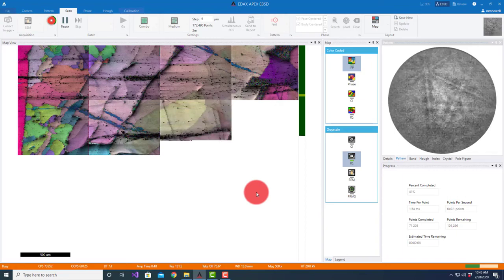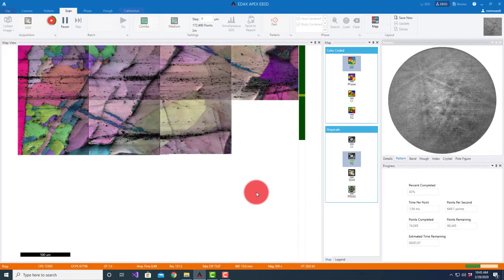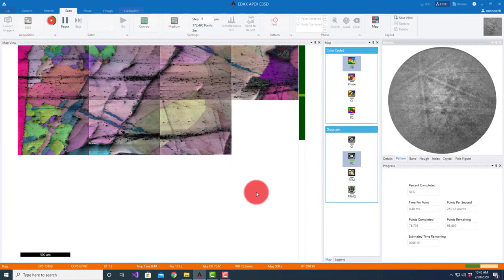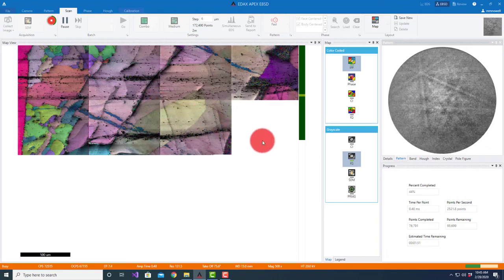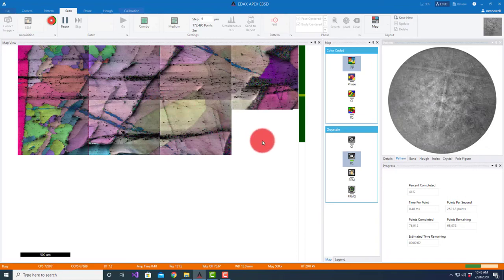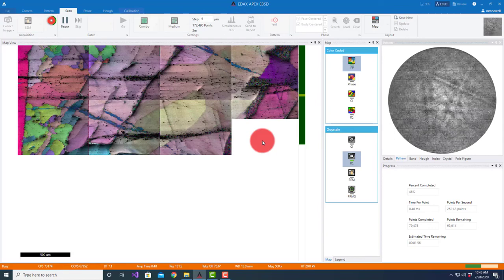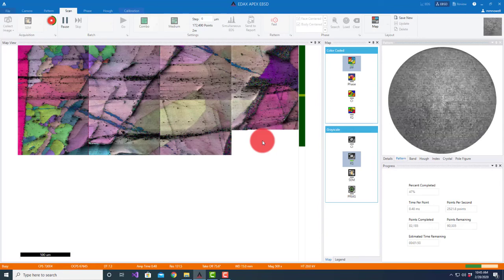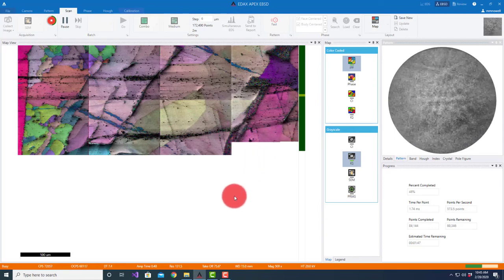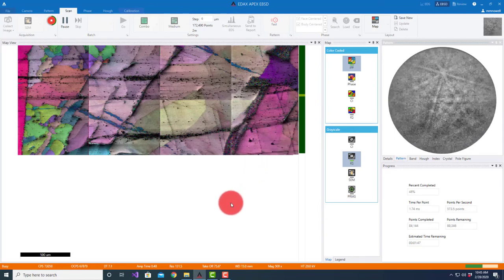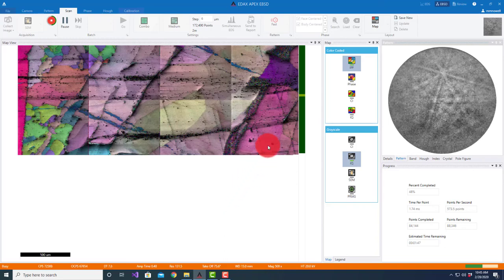Here you can see one that's not as perfect. That's always one of the tricky parts - is your sample perfectly at 70 degrees across the full field of view? Here it seams pretty nicely, here it's a little bit offset. But generally if we're looking at a large area, it's still going to give us a good idea of the grain structure, the grain size, and the texture.